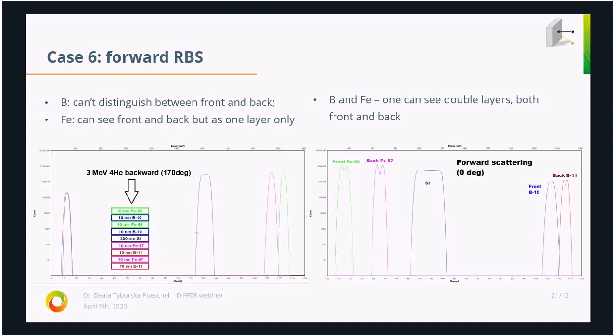But generally, when you consider this entire system, the RBS system preserves the conservation of energy and momentum. And when you solve equations for it and you calculate the so-called kinematic factor, which simply tells you the energy loss between the incoming and backscattered beam, then analyzing that equation from that physics, you can see in terms of the energy loss that the best depth resolution comes exactly for the forward scattering, which however usually is not used in most laboratories because usually people don't deal with thin membranes.